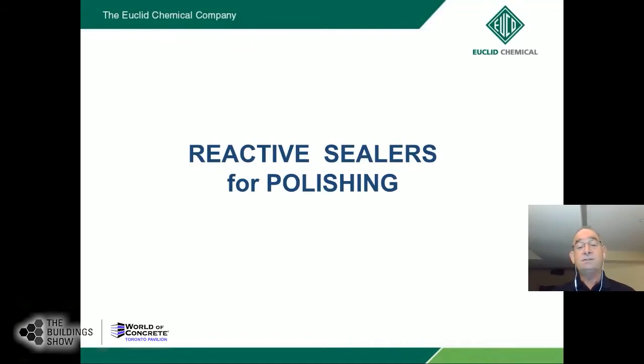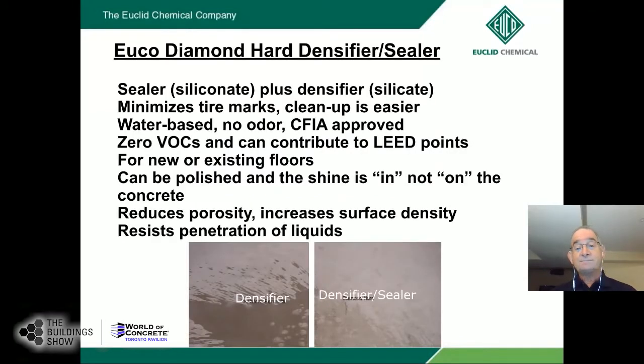With these polishable materials, we do use reactive sealers for the polishing in order to help densify and seal the surface. Euco Diamond Hard is our densifier sealer that's most often used with these applications. It's a sealer and densifier, as I mentioned. The sealing part is a siliconate portion of it, and then it's also made with a silicate, which gives us densification. This allows us to minimize tire marking, particularly if you're using it in warehouse applications. It's easier to clean. It's water-based with no odors. We do have CFIA approval for it, so if you're dealing with food processing facilities, it can be used for those applications. So the zero VOCs also means that it can contribute to LEED points as well.